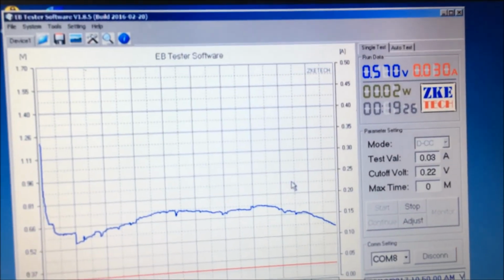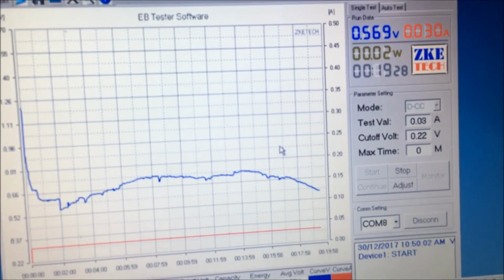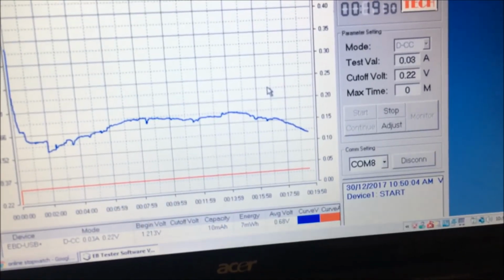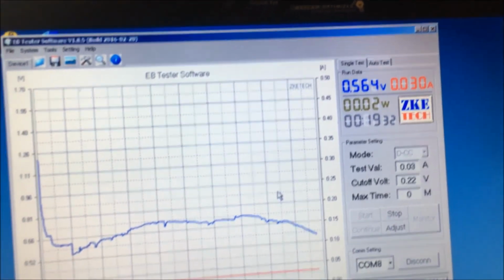We're coming to an end actually. 20 minutes nearly. Oh, it's still at 0.5 though. So I'll put that copper cell in and see if it performs back to a 1 hour or 1.5 hour run. And then we can sort of say that the copper cell disintegrated this time. Copper has plated on the carbon zinc electrode though, for some reason.